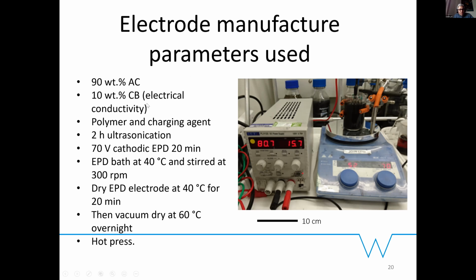The amount of activated carbon and carbon black for improving electrical conductivity. We varied the polymer and charging agents. This ultrasonification was done in order to disperse the activated carbon into the particular solvent, especially because if we leave them lying around for 15 minutes to half an hour, all of them aggregate at the bottom. So it's not possible to then apply electrical charge and make them migrate to the electrode surface. So it's important to use sonication, have them well dispersed in the solution, and then immediately start the process so that we can get as much deposition as possible.